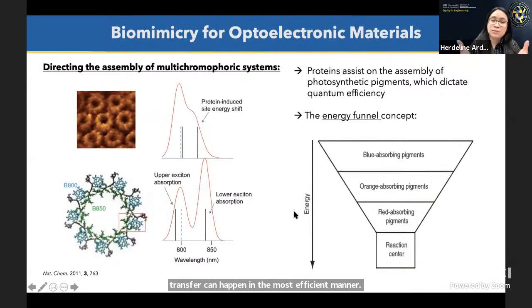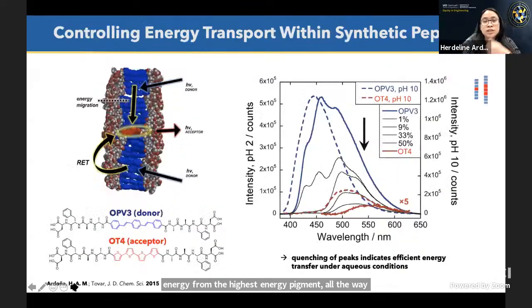This is consistent with the idea of funneling the energy from the highest energy pigment all the way to the reaction center. So going back to our biomaterial, the pi conjugated system, we asked whether we can incorporate more than one chromophore, more than one electroactive unit. In this case, we have an energy donor, which upon light excitation, transfers energy from the donor to the acceptor.